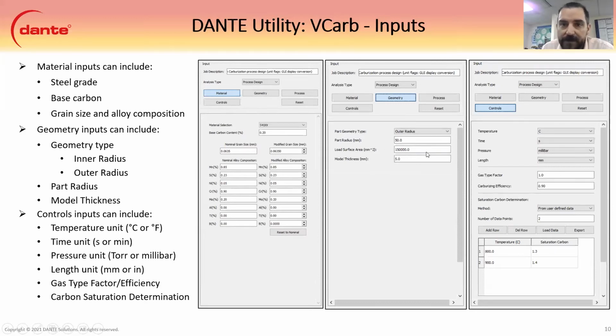And a load surface area, which also defines how much gas is used during your process, during the boost schedules. And then the model thickness is how long it needs to calculate for. So this is how deep your model is. And then as far as the controls, we can change temperature to Fahrenheit or Celsius. We can do time in minutes or seconds. We can do your standard imperial units or SI for all these types of things. We have a gas type factor that if you're using acetylene, we usually leave that as 1. But if you're using some lower grade, let's say propane or something like that, you want to bring that number down a little bit in order to account for how well it can carburize. And that's pretty much it for VCarb.